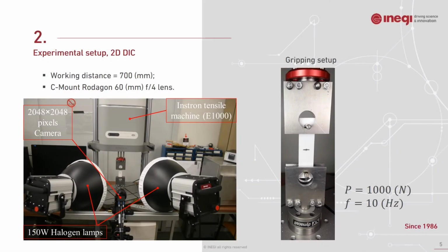As can be seen in the figure, the experimental test has been done by an Instron machine with the capacity of 1 kilonewton. Two halogen lamps were positioned in front of the specimen. A camera has been positioned in front of the specimen, and the gripping system is shown on the right side. The maximum capacity of the machine has been used, so the applied load was considered as 1 kilonewton with the frequency of 10 hertz.